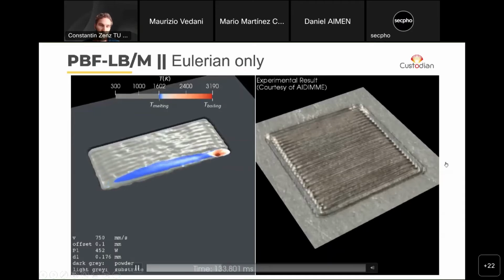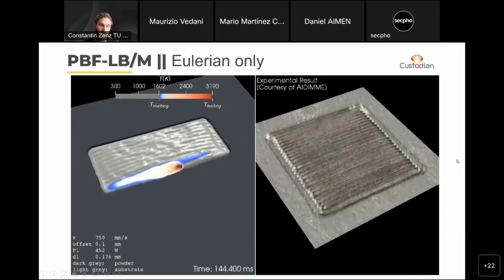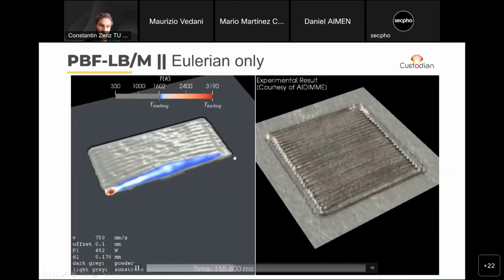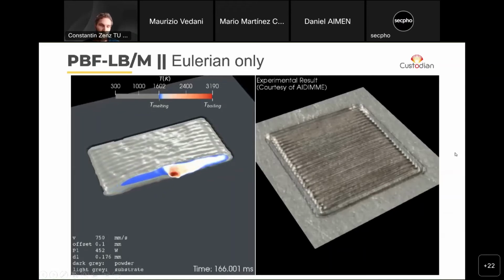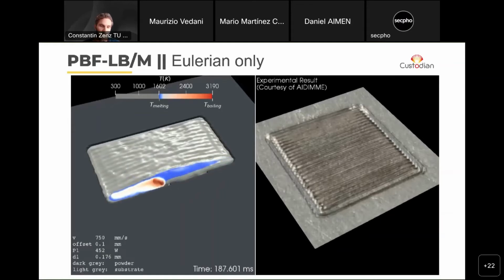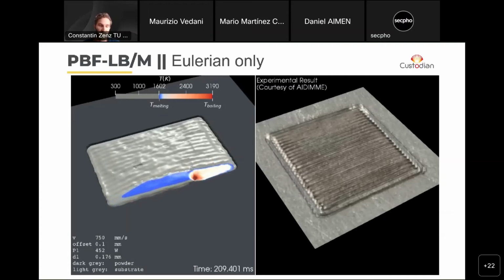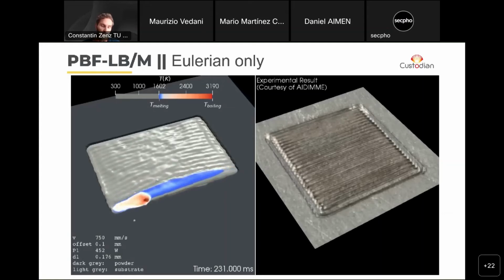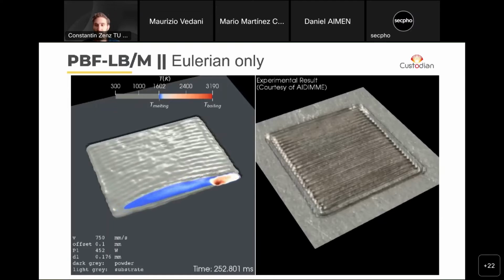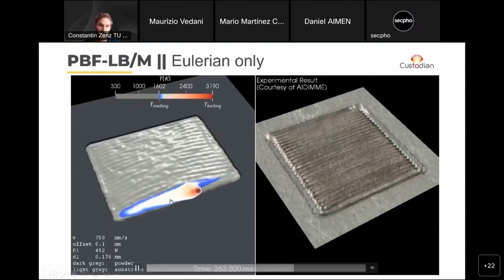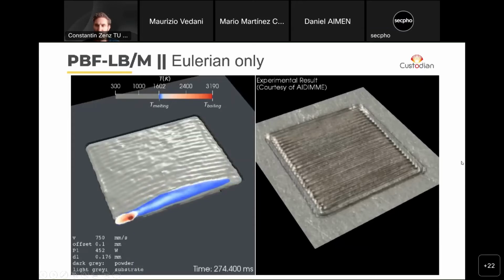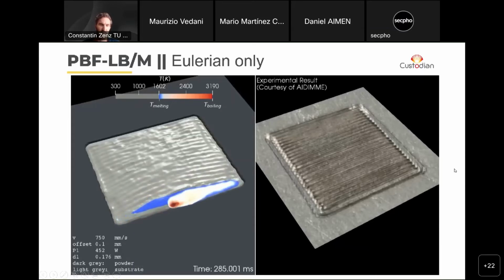Everything that is colored from red to blue, this is liquid material. So in this simulation, you can see, for example, some heat accumulation as the top of the melt pool of the previous track is always still liquid and not solidified yet. So this is kind of how the simulations look that we performed during the custodian project. These are now multiple tracks. This is about 50 tracks to perform a 5 by 5 millimeter area of processing.